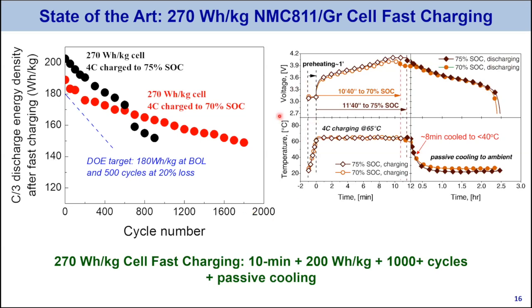And if you look at the detailed cell voltage and temperature curves, it's very interesting. First of all, you see one period of preheating takes less than 1 minute, in which basically the cell voltage remains the same. There's virtually no electrochemical activity. It's just the charge current passing through the nickel foil preheater, heating the cell from ambient to 65 degrees Celsius rapidly. Then after that, it switches off and the charge current is charging the battery. Voltage goes up and you charge it to 70% or 75%. And after a short rest, it's followed by C/3 discharge, and nicely outputs the energy.